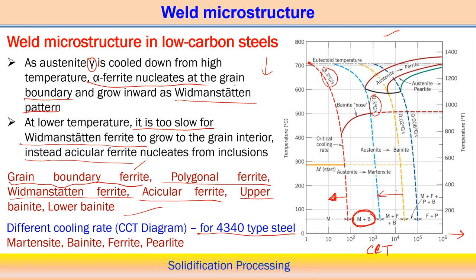So between these two cooling rates, gradually towards the right hand side the cooling rate is actually decreasing, and all these different colors represent the constant cooling rate over this curve. At the different cooling rates, we can get this zone, which is martensitic plus ferrite plus bainite. So ferrite structure is gradually formed at the low cooling rate. Here you can see the martensitic structure, ferrite structure, pearlite, bainite structure, but at a very low cooling rate, 0.006 degrees centigrade per second, we can get the mixture of ferrite plus pearlite.